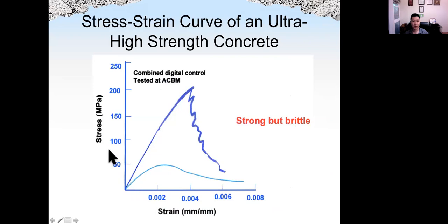Here shows the stress-strain curve of ultra-high-strength concrete compared with normal concrete. The strength is very high. The slope, which is the E value, for high-strength concrete is higher compared with normal concrete. And we can also see high-strength concrete tends to be brittle, which means after the peak load it will fail suddenly, compared with normal concrete, which has much longer post-peak behavior.